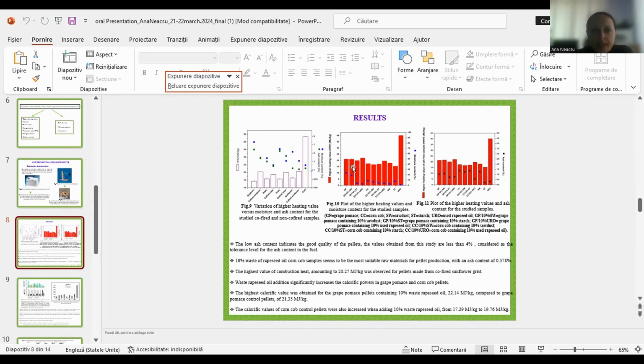Addition of 10% of waste rapeseed oil in the samples of corn cob seems to be the most suitable raw material for pellet production. The highest value of combustion heat, amounting to 20 megajoule per kilogram, was observed for pellets made from co-fired sunflower grease. Addition of waste rapeseed oil significantly increases the calorific powers in grape pomace and corn cob pellets. The calorific values of corn cob control pellets were also increased when adding 10% waste rapeseed oil from 17 megajoule to 19 megajoule per kilogram.